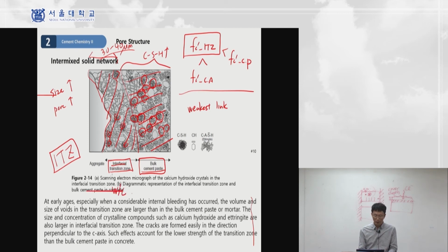You will learn later, but the short answer to that question is that the water to cement ratio at that specific zone is higher than the water to cement ratio at the other part. Okay, so that means aggregate contains water itself, or it can absorb mixing water first. Before that water reacts with cement, it will absorb water very, very fast. So locally, it has higher water to cement ratio characteristics.